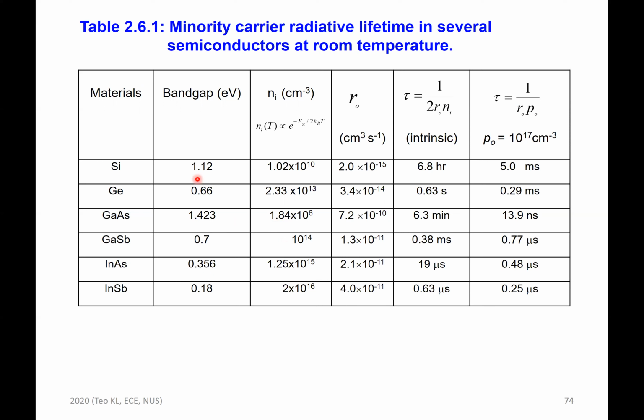Now, if we look at silicon, this is the recombination coefficient and it can be measured experimentally. So we'll just quote the value here. The recombination lifetime for intrinsic semiconductor is 1 over 2R naught N naught. So if you plug in these two values, you realize that minority carrier lifetime is 6.8 hours in silicon.